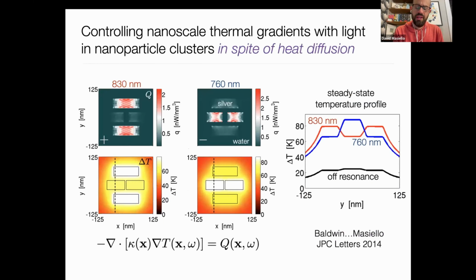And so we started thinking about, well, what are the consequences on the heat power absorbed and the temperature rise that would result from driving this coupled system at these certain wavelengths that would excite these linear combinations of normal modes. And this was really quite surprising to us. So we calculated numerically the heat power absorbed, that's these upper two plots, at two different wavelengths, the in-phase and out-of-phase linear combination wavelengths, localized to the outer two or inner two rods within this structure.